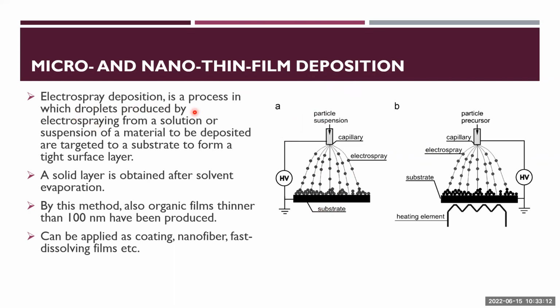So here the electrospray deposition is a process in which the droplets produced by electrospray are deposited on a target substrate. Like you have here, let's say, aluminum foil or a metal material, because usually we need to use a conductive material. And here is the needle or the capillary. Between them, we apply a high voltage power supply, and we flow the liquid from here. Then it will spray.